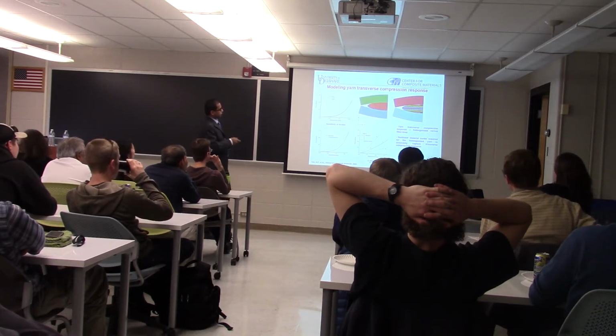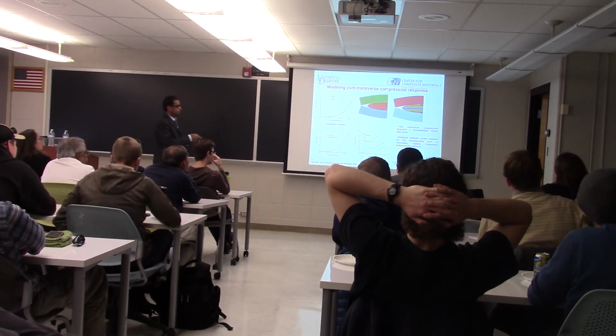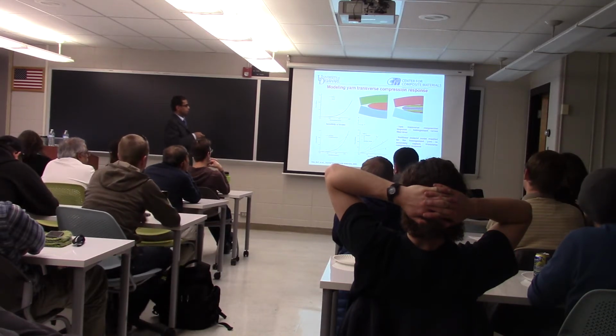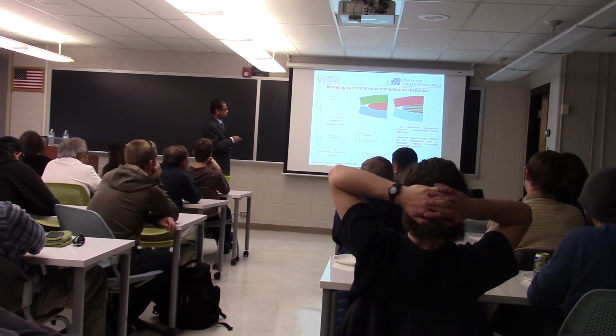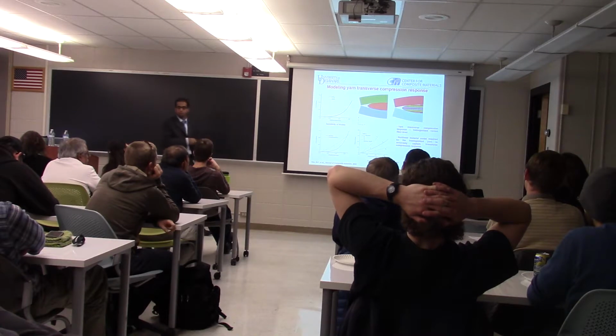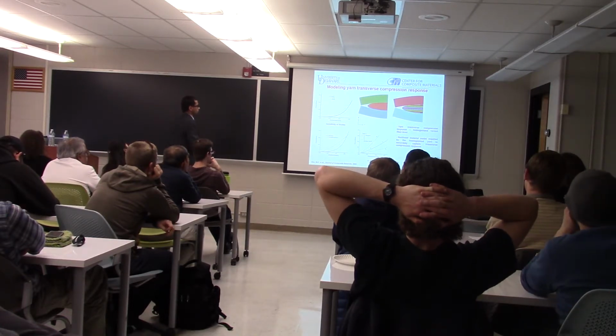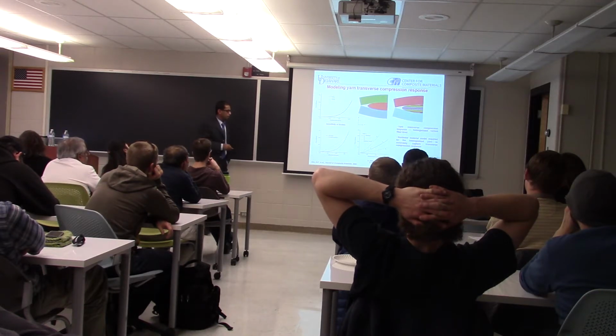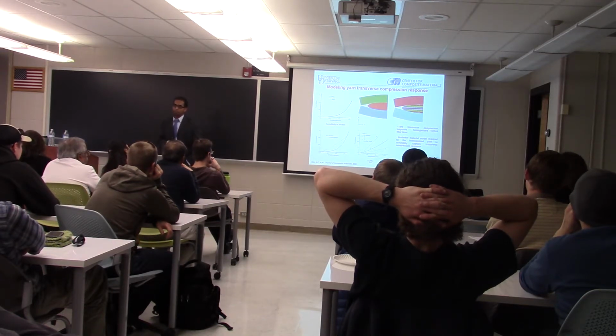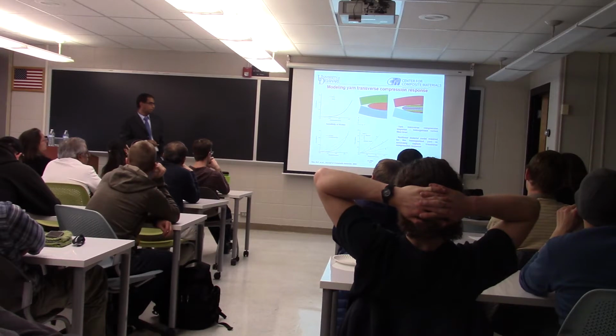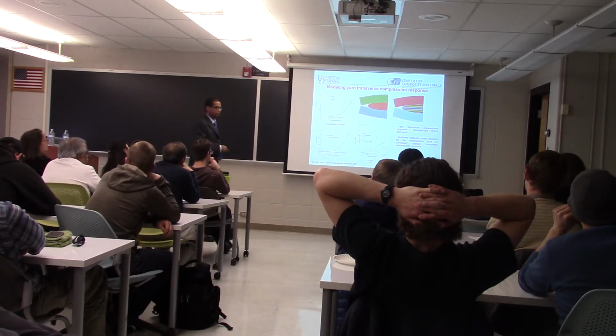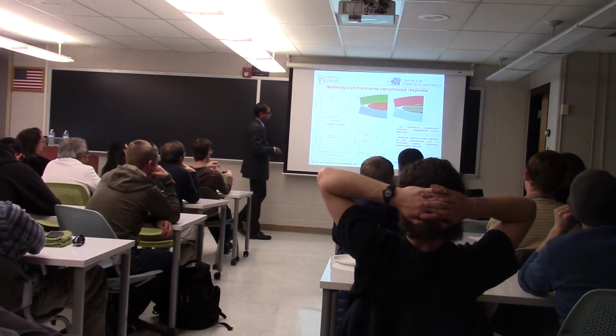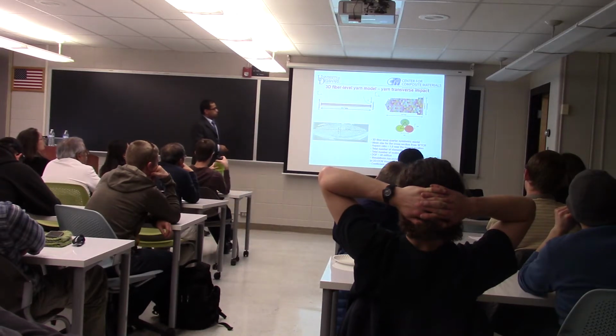And a sensitivity study of the coefficient of friction between the fibers indicates that there may be a dependence on the friction coefficient, with a larger force required to compress the fibers with a larger friction coefficient. So these studies indicate that fiber-fiber contact may play a role in the spreading and deformation of individual fibers. Now the natural next step is to understand these fiber-fiber interactions during the impact.